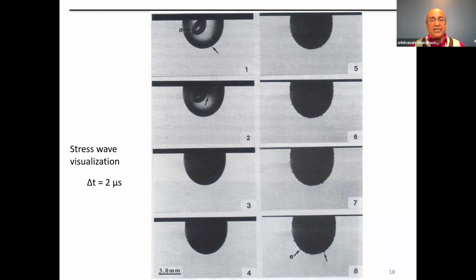And in water, you can use a technique called Schlieren photography, which makes use of refractive changes caused by shock waves or stress waves to see if you can visualize whether there were any stress waves, and we couldn't see any. And in fact, that arrow on the top left, frame 1, points to a little bubble that is sticking to the glass surface. And if you come to frame 8, when the explosion is complete, the bubble still stays stuck to the glass. That means if there were stress waves too, they weren't even strong enough to dislodge the bubble. So we ruled out stress waves as the cause, confirming that it's the crack propagation from the tail that is the reason, and the bifurcation.